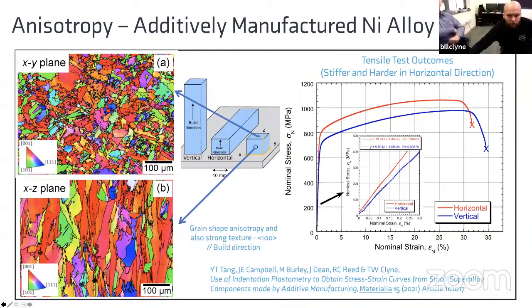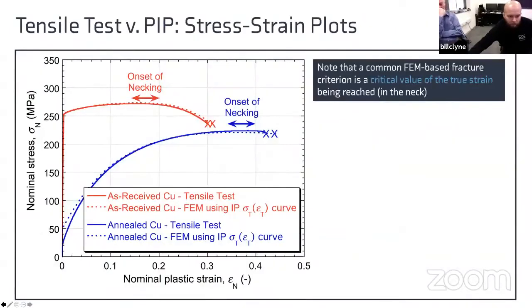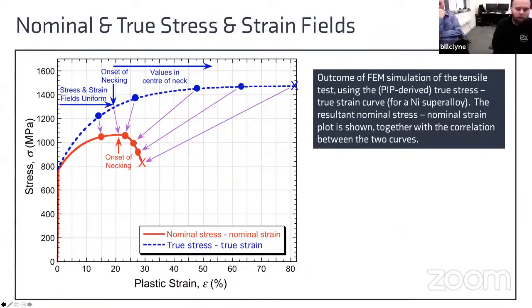Yeah. So we're not considering the effect of voids in the onset of necking. If we look at this plot here, you can see that the nominal stress builds up to the maximum at just under 1100, and then the neck begins to form, and that is just a geometrical effect, and indeed was predicted by Considère a long time ago. So in terms of the beginning of the formation of the neck, it's a geometrical thing. You can predict it both from FE or just from converting the Voce equation in its true form into the nominal form, and again you'll predict a maximum, and it's then just the instability that will lead to the